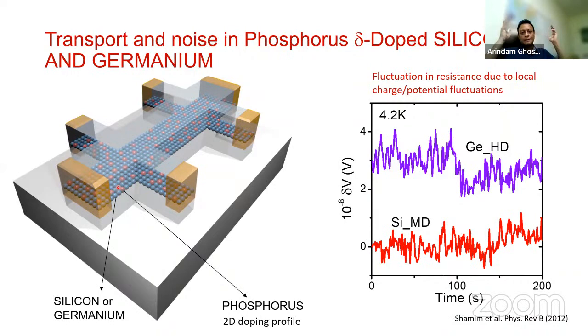So bulk doped semiconductors have been here for a very long time, in the 1970s, 80s, or even earlier, actually 1943 was the first paper. But this is different. This is different because now there is a technology through which the dopants can be put in one layer, and this gives you a two-dimensional semiconductor in some form. We measured noise in that, and you can see typical noise in those is extremely low because they are very well stabilized, with a noise level of 2 nanovolt really.